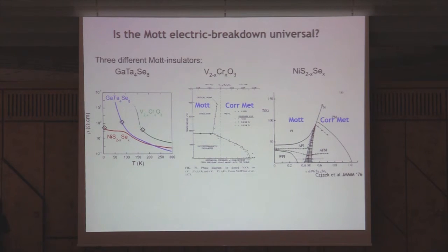Very well. So one immediate question is, is this thing intrinsic to Mott insulators, or is it just peculiar to the GTS system? So the idea was to go and look for the classic examples of Mott-Hubbard systems that we know, V2O3 that I mentioned before, and nickel sulfur selenide that was also mentioned in the talk the first day. So these two systems have this specific first order line in which you can melt a metal into an insulator. You heat up this metal, this is a correlated metal, and it becomes an insulator, presumably destroying the quasi-particle peak. This first order line ends in a high temperature second order critical point, and here the same thing, you have a correlated metal and the first order line tilted that way.